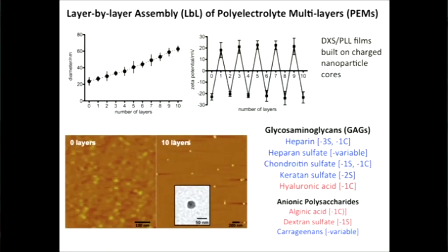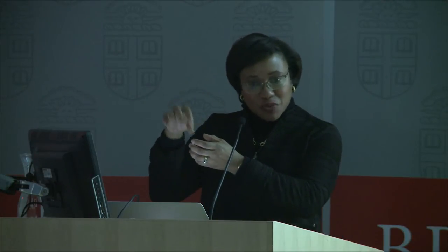But first, some of you are thinking, wait, how are you going to put this stuff on a nanoparticle? So there are ways in which this is done. The one that's most common is to take a centrifuge tube that contains your solution of nanoparticle. You introduce or titrate in your aqueous solution, wait a certain amount of time for adsorption to take place, and then centrifuge that down, decant and isolate the nanoparticles, and then do the next step. It takes a lot of work, and we're actually working on a much faster way of doing that, which during Q&A I'd be happy to address.